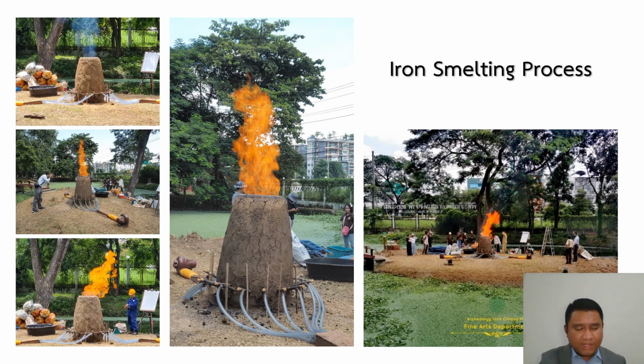Next, we start the smelting process by adding charcoal until the furnace is full, and fill the air through all 16 blowing holes, which creates swirling air in the furnace. After that, the ore was added alternately with the charcoal fuel. The time interval is 5 to 10 minutes, mainly observing the combustion characteristics and keeping records.